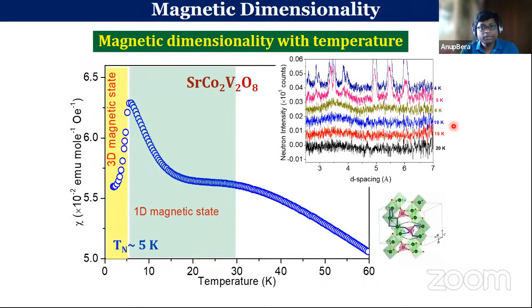Now I come to my system, the spin half chain compound. This is the susceptibility data shown as a function of temperature. When we cool the system, since the topology is one dimensional, it goes to the low temperature 3-dimensional magnetic ordering, and before that, at higher temperature, it goes to a state which is known as the 1D magnetic state, which is experimentally confirmed from the neutron diffraction study. This is the magnetic diffraction pattern at different temperatures. As we go down, we see a broad diffuse scattering appearing in the diffraction pattern due to the 1-dimensional magnetic arrangement. And then at low temperature, when the 3-dimensional magnetic ordering sets in, we see the magnetic Bragg peaks.